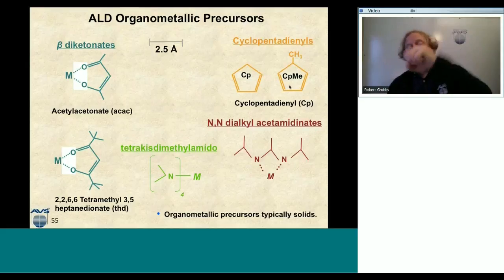So you have a platinum atom, you have 3 methyls that stick down as a tripod, and then you've got this CP ring that sits on top. And that's the precursor that's used for platinum ALD. Then you've got your tetrakis dimethylamido. These can come in different flavors like zirconia or hafnia, and those are still primarily the precursors of choice for those particular metals to make a hafnium oxide or a zirconium oxide.